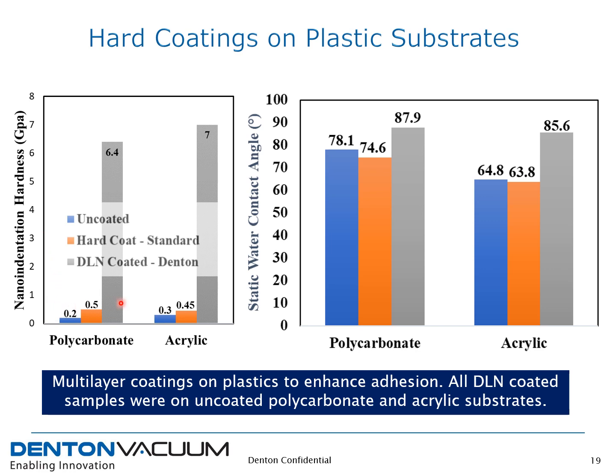This bar graph shows a comparison of the nanoindentation hardness of polycarbonate and acrylic substrates. As you can see, the DLN coated substrates have a hardness that is several times higher than the uncoated or even the substrates with the commercially available standard hard coat. Also, the static water contact angles are higher for the DLN coated substrates compared to either the uncoated or the standard hard coated substrates. In fact, these surfaces could be made even more hydrophobic by the surface treatment that we mentioned before.